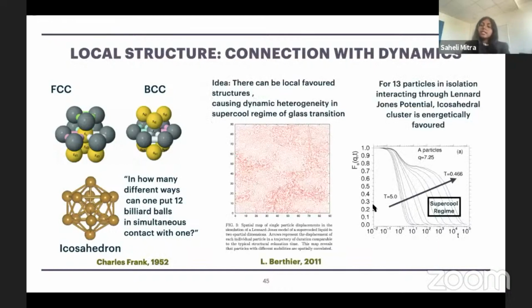So as we have discussed earlier, in the supercooled regime of glass forming materials, the relaxation time increases a lot. And in that regime, the system becomes dynamically heterogeneous. In the middle, I have a plot of a system interacting through a Lennard-Jones potential, and with each particle there is an arrow associated, and the length and direction of these arrows represent the particle displacement over the alpha relaxation time. We see that the parts with high displacement and parts with low displacement are actually spatially correlated.